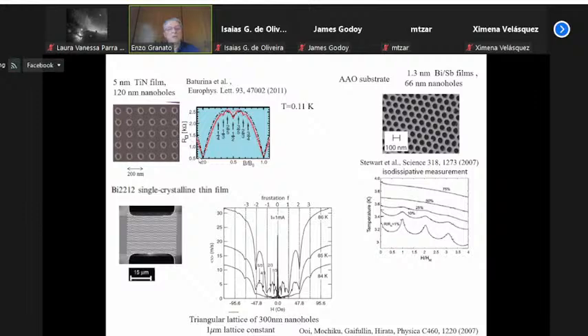But again, as a function of frustration, you see a primary minimum at the integers, a secondary minimum at 1/2, and very high order minima here. This is a square array of holes, and between the large regions you can regard this system as made of superconducting arrays with constrictions. There's a constriction between one plaquette and the next, and you can model this as a square array of junctions.